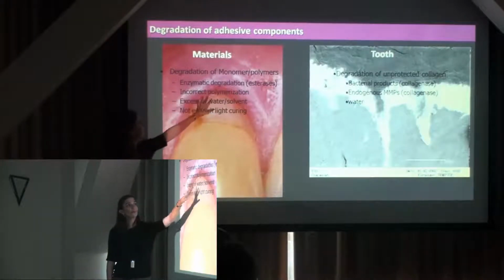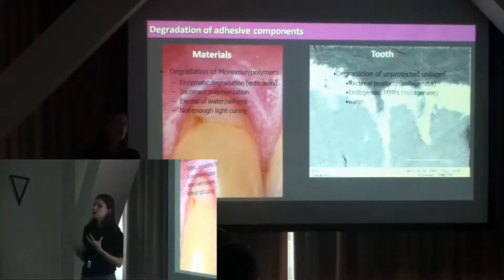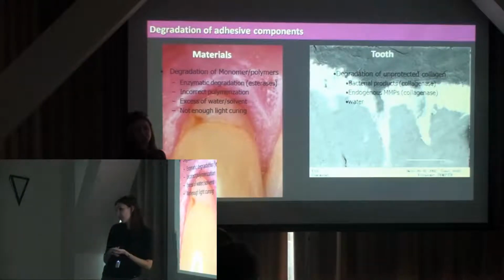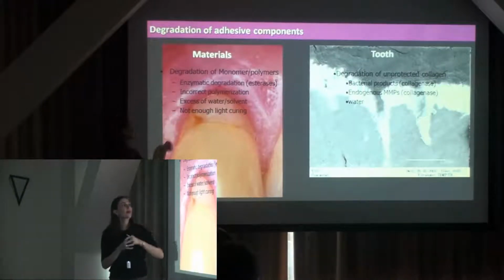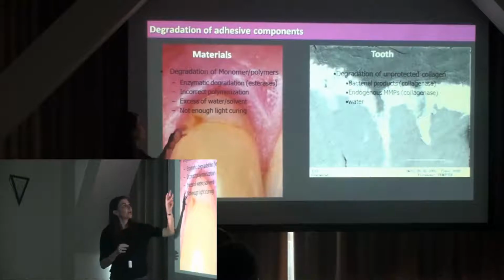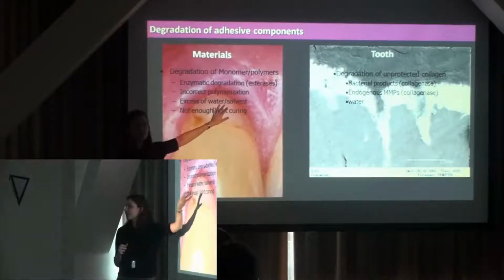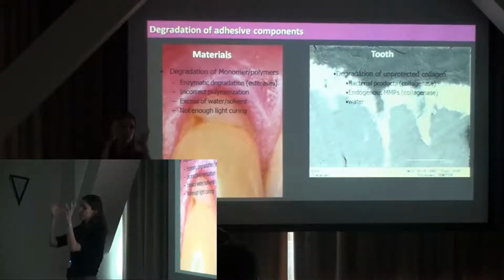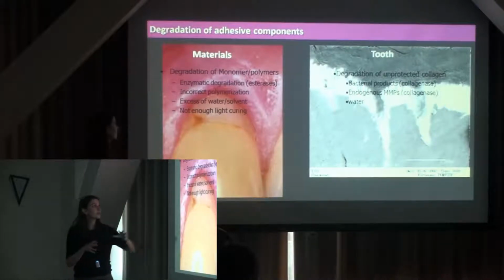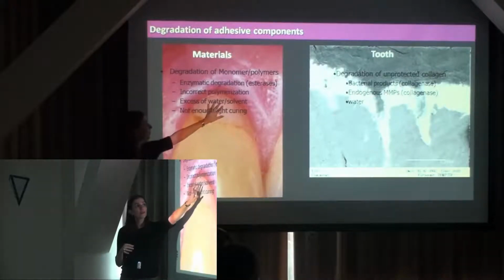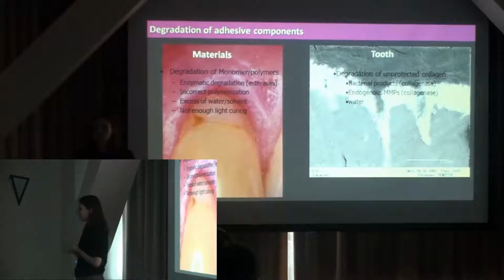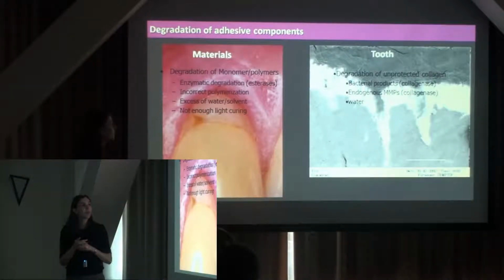We also have problems with the polymerization. Most of these things are done with the light, and you never get 100% polymerization. We actually get around 60% or so. We need some solvents in here to make this material fluid enough to infiltrate over that surface of the tooth. So if we don't appropriately get rid of these, they also don't let the material polymerize as well.